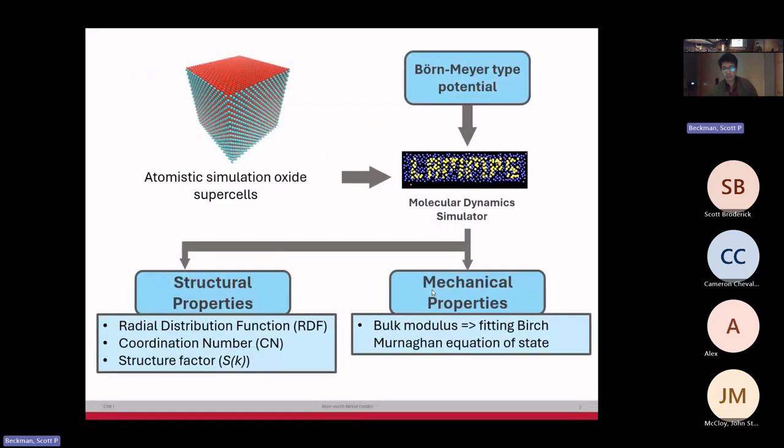We used molecular dynamics simulations to understand the structural properties of single crystal ceria and yttria-doped ceria. We basically calculated the basics of the structure like radial distribution function and coordination number, and also structure factor.